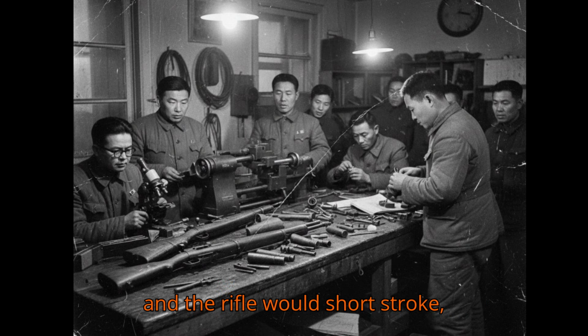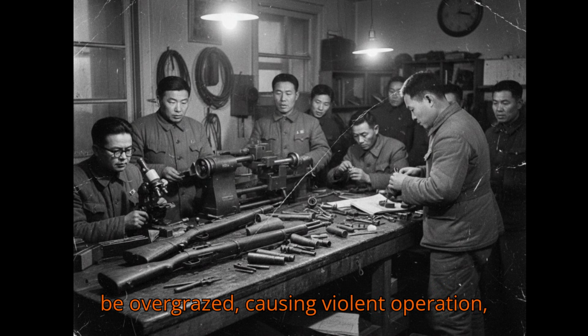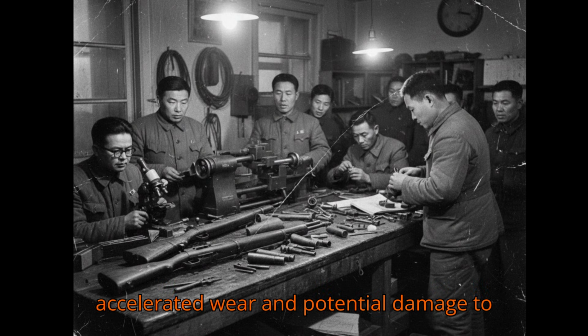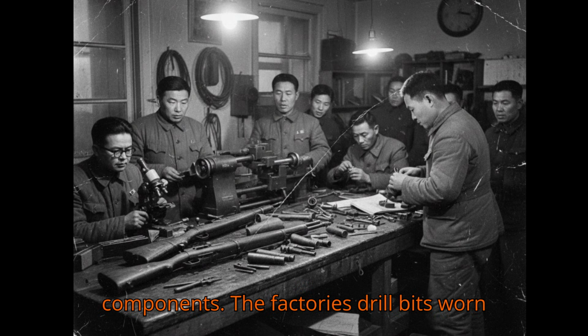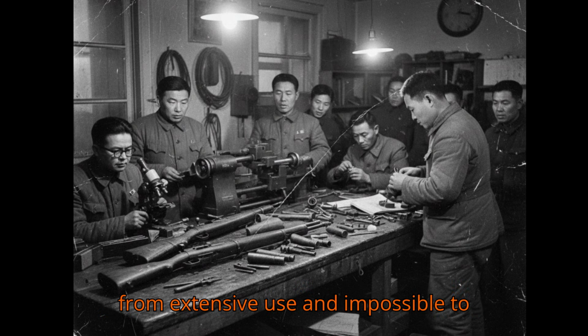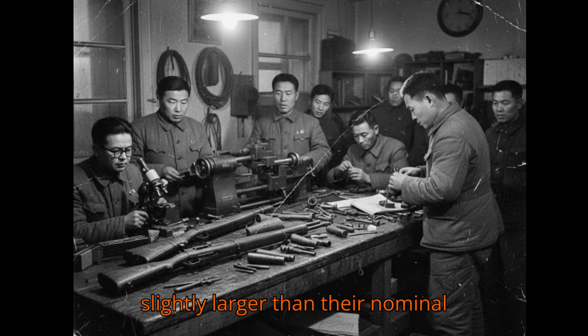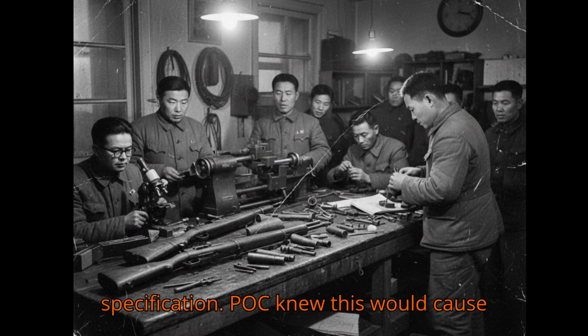Too small, and the rifle would short-stroke, failing to fully cycle the action. Too large, and the system would be overgassed, causing violent operation, accelerated wear, and potential damage to components. The factory's drill bits, worn from extensive use and impossible to replace with American supplies unavailable, tended to produce holes slightly larger than their nominal diameter. The gas port ended up at 0.093 inches, nearly 20% larger than specification.